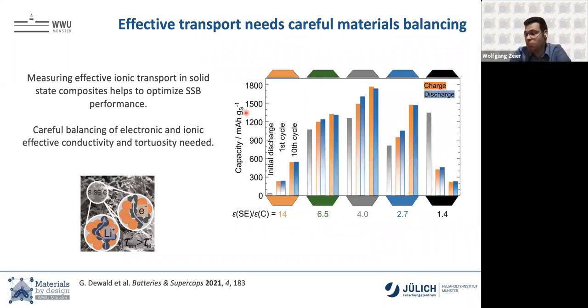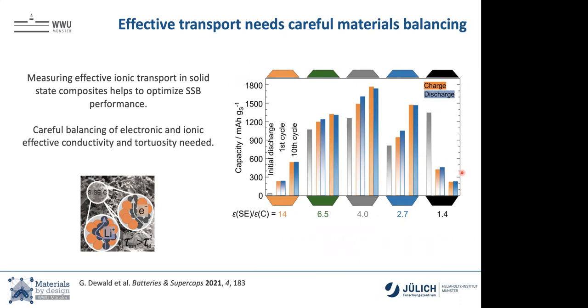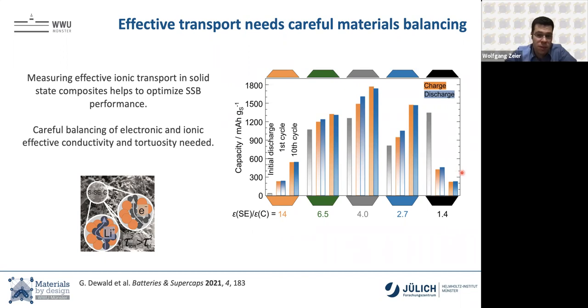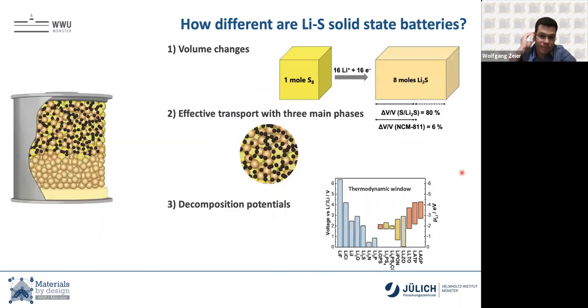But what we do learn from all of that is that it takes careful balancing of the effective transport, in this case, the lithium ion transport, but also your electronic transport. If your electronic conduction is too low, you have the same problem. And so, for instance, if you play with the volume fraction of your solid electrolyte and your carbon, keeping the sulfur ratio the same, you can optimize the actual capacity, so the amount of charge that you can store in these sulfur batteries. But this is quite doable. It's just a big engineering problem, I would say.